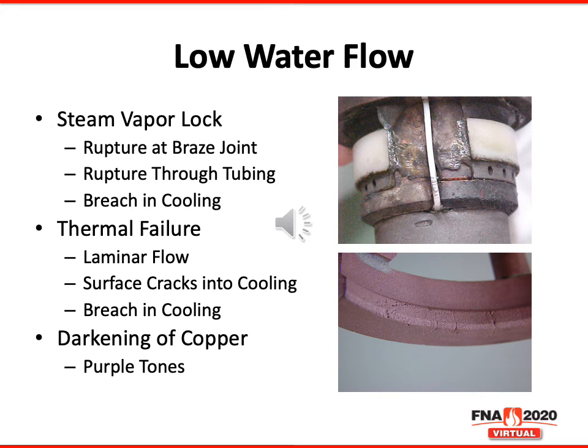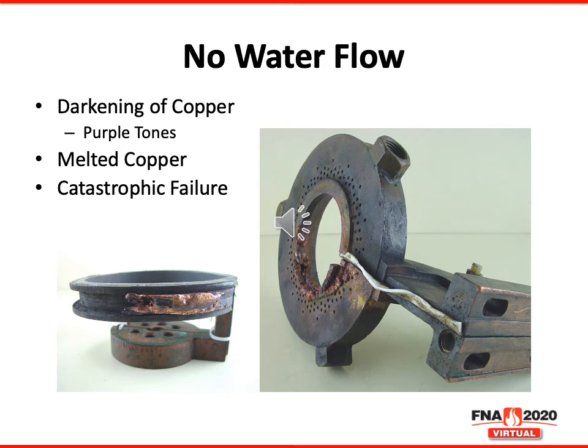Low water flow is sometimes identified by darkening of copper with purple color tones on the cooling return side of the inductor coil. Induction tooling components cannot survive without water cooling. A no water condition is easily recognizable as shown in these images. Symptoms include darkening of copper with purple color tones, melted copper, and catastrophic failure. Catastrophic failures caused by a no water flow condition cannot be patched and require a major rebuild or replacement. It is a wise investment to have a flow indicator on the machine that prevents operation if there is no water flow.